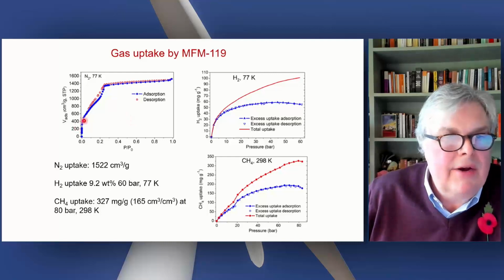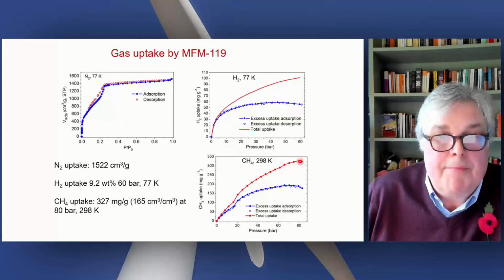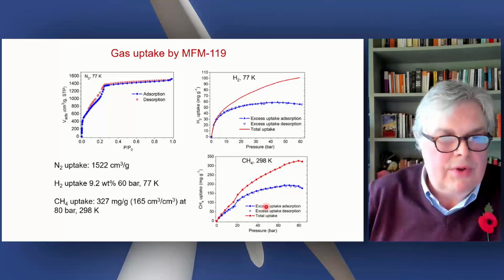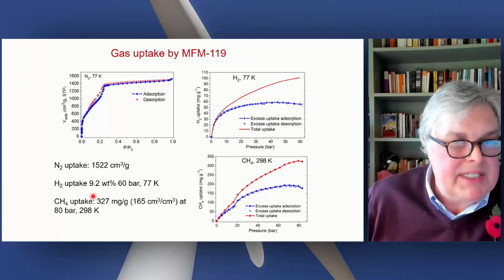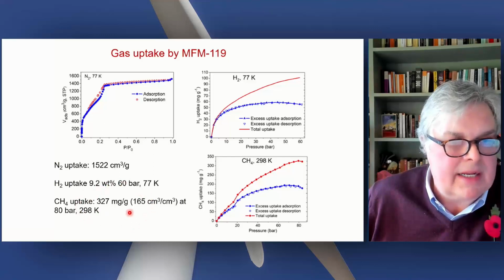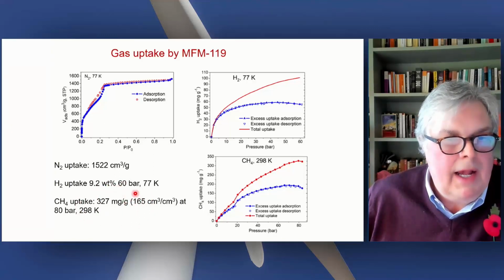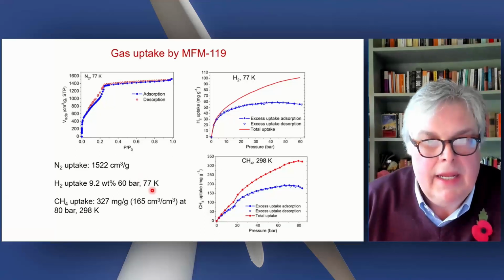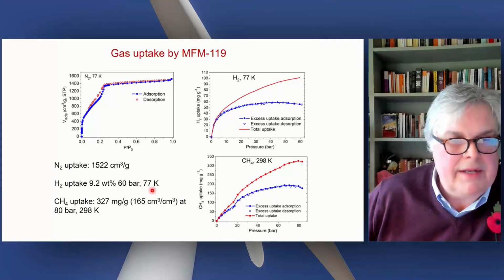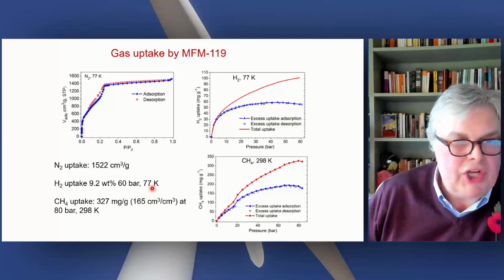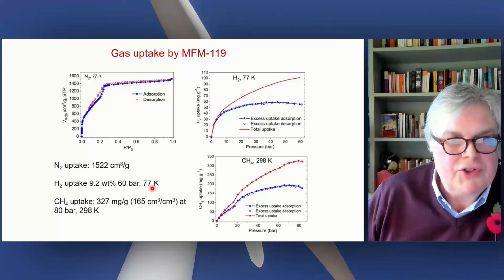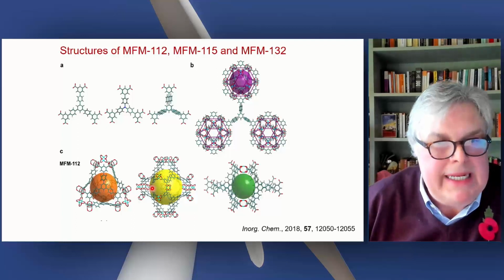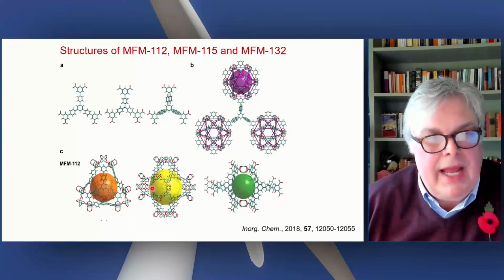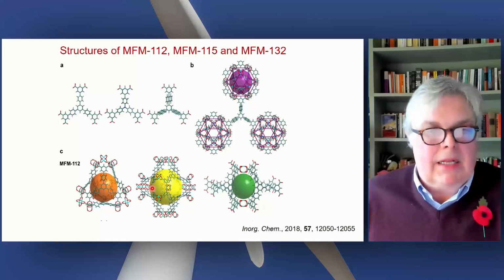The gas uptake for dinitrogen, for hydrogen, and for methane is shown here. This is all very nice, very high uptake, particularly for methane. This is a very high uptake for methane under these conditions. But I emphasize again, the problem with the hydrogen uptake is that the good uptake occurs, of course, at 77 K. And there is still a lot of work to be done in raising that temperature. So this is a real challenge for MOFs in terms of hydrogen storage. We probably need to go to systems that have ligand binding sites as well as metal binding sites.